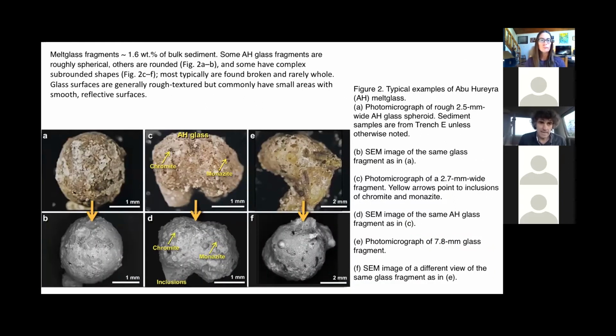Let's look at some of these objects. There's a lot of glass there. Some of them are almost a centimeter in size, but it's very rare to find an intact glass globule. These are some of the few cases where we could find intact glass, complete and not broken. Most of the time it's broken. We can see the optical image on top and the SEM image at the bottom. This glass very often had weird minerals in it, like chromite and monazite. It's not just the presence of the minerals, but that there was evidence of partial melting of these minerals, which gives you a clue about the temperature of that melt at the time of melting.